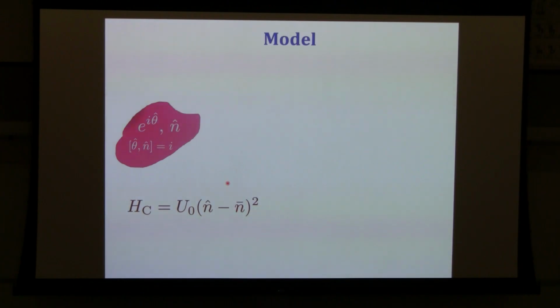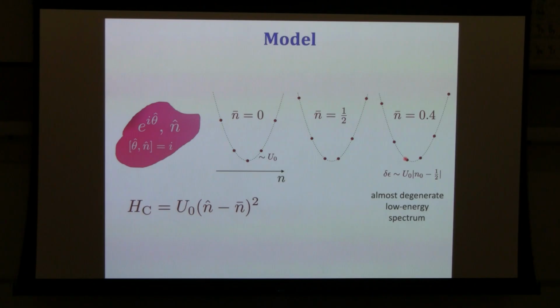n bar does not have to be an integer, and n bar is somehow a function of the local electrostatic environment, if you like, of this puddle. So that's a continuous variable, and the energy spectrum of this puddle would look like this: just discrete integer n's have a parabolic energy as a function of n, and there's something special that happens. This n bar we'll treat as a random variable. Something special happens when this n bar is exactly half. In that case, the two lowest energy levels in the system would be degenerate, basically n and n plus 1 Cooper pairs. If we tune it a little bit away from half, then we'll lift this degeneracy. So we'll treat this n bar as a random variable, which is uniformly distributed. There's no particular reason why a particular puddle would favor a particular value of n.